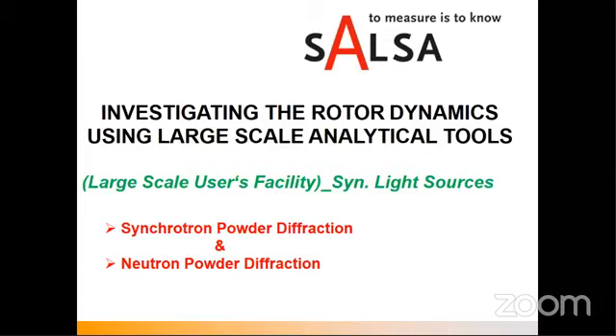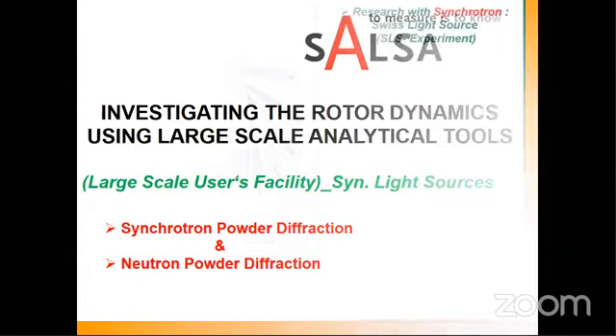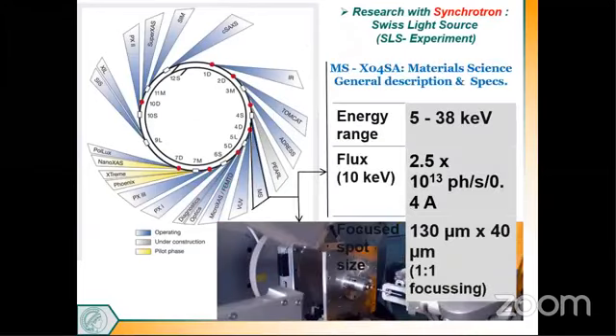Now, I use synchrotron powder diffraction and neutron powder diffraction techniques from the Paul Scherrer Institute in Switzerland, because I was privileged to be at Max Planck. So it's not a difficult job to measure these samples via synchrotron powder diffraction. We used the MS beamline, which has these parameters. The focus spot size is 130 micrometers by 40 micrometers, and we used a beam energy of 8 kilo electron volts to measure our samples.